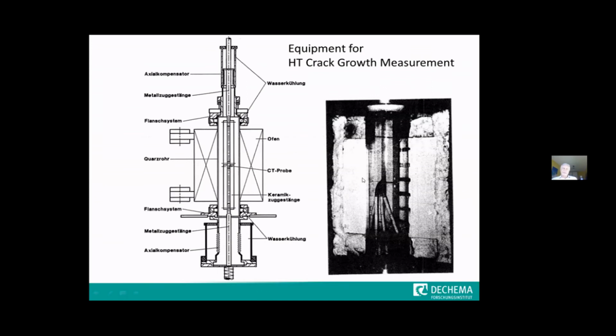This is a pretty old one, which shows the equipment that we built up for this case, which is a tensile testing machine. And there we have ceramic pull rods here, and in the middle there's a CT, a compact tension specimen. So I apologize, this is in German, but I can explain it to you. So we have a furnace here, and we have an environmental chamber around it. We have the ceramic pull rods, and we have this specimen where we do the crack growth measurements here.